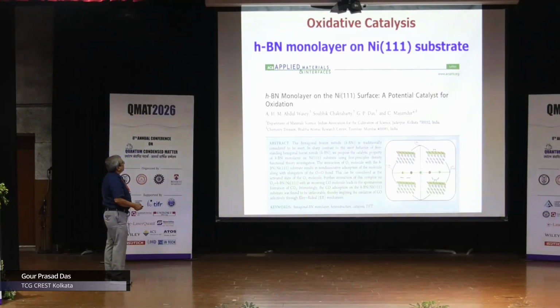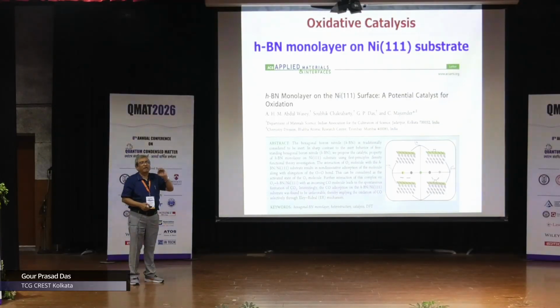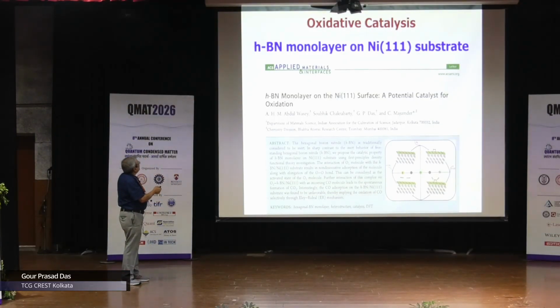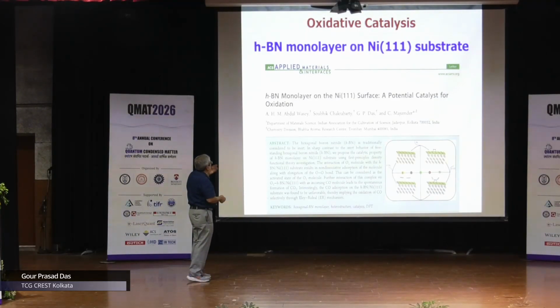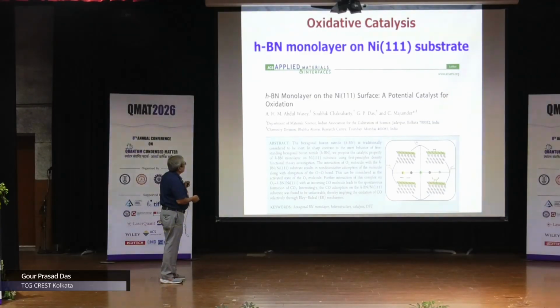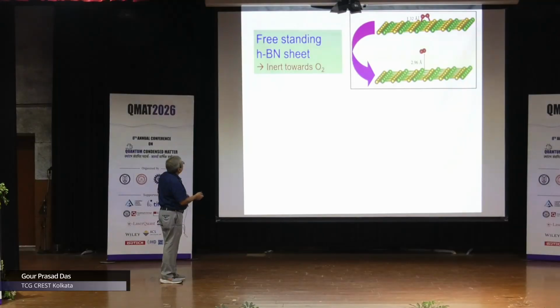Okay. So just one example I will tell you, which is definitely something to do with the bonding at the interface. So the HBN monolayer on nickel 111. This is some paper which I don't remember which year, sometimes around 2015 or so, I think. So what happens, I will tell you. When we bring oxygen on freestanding HBN, hexagonal boron nitride, it does not stay, it goes away. We have done it by molecular dynamics.